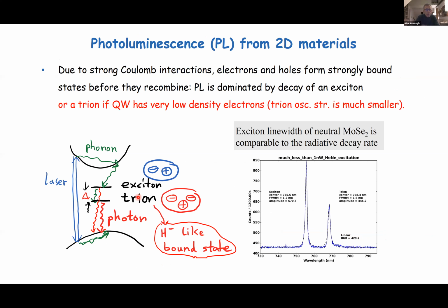Okay, so I was going to talk about the photoluminescence measurements, not going into efficiency. In these measurements, you take a high energy laser and generate electron hole pairs. They relax, and because the exciton state has lower energy by 200 milli-electron volts, the emission takes place after the electron hole pairs relax by phonon emission to form an exciton. This is also standard in 3-5 semiconductors, that the intraband relaxation is generically faster than interband.